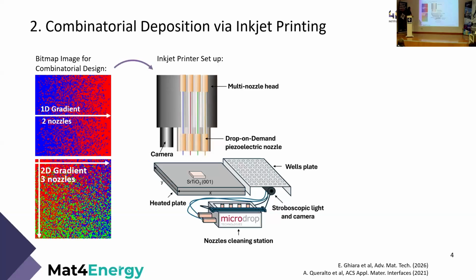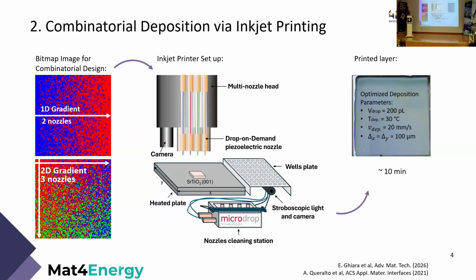Then the deposition happened through an inkjet printer supplied by Microdrop Technologies. We supply a combinatorial design to the machine via bitmap image. Basically, in the image, we have different pixels which codify for the ejection of a specific drop from a specific nozzle, which contains a different solution. So once again, after a long optimization process, we are now able to deposit combinatorial samples in less than 10 minutes, in which different precursors directly mix on top of the substrate.